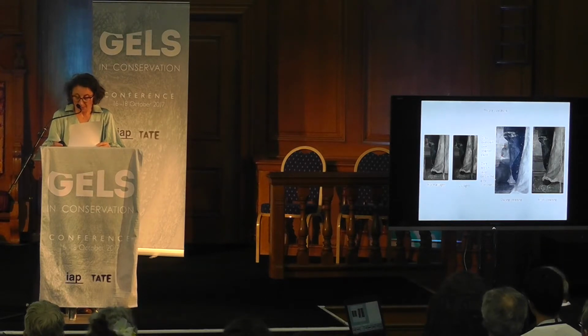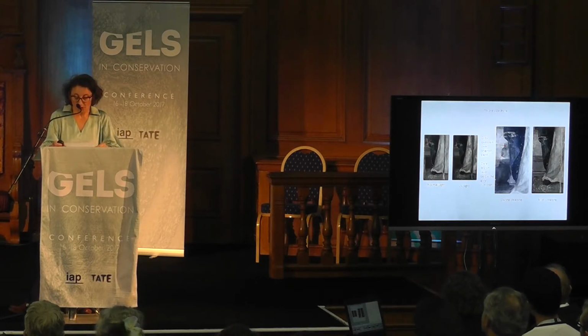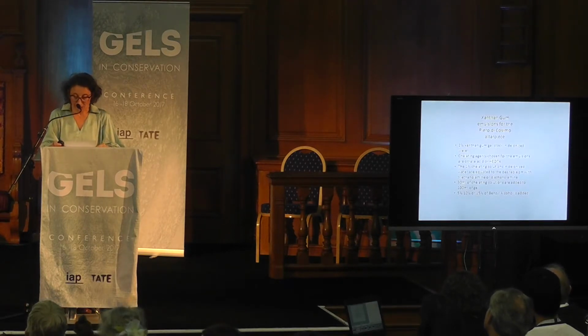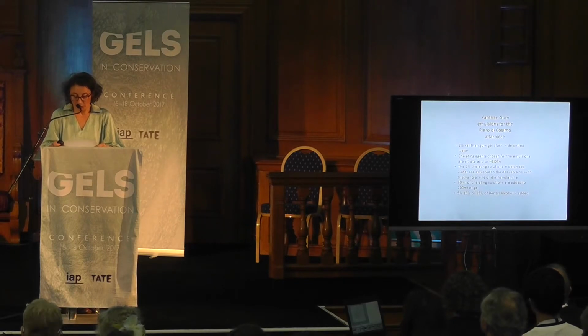The cleaning started at the top edge of the pedestal where the original paint film was visible and progressed towards the lower edge. Though the acetone benzyl alcohol gel was useful in softening the top layer of gray overpaint, the lower brown layer was more resilient. For this layer, different emulsions were prepared from a 2% stock gel of xanthan gum and deionized water. By varying the three key elements, adjusting the pH, changing the chelating agent, and altering the concentration of the emulsified solvent, the gels were modified to the solubility parameters of the brown layer.